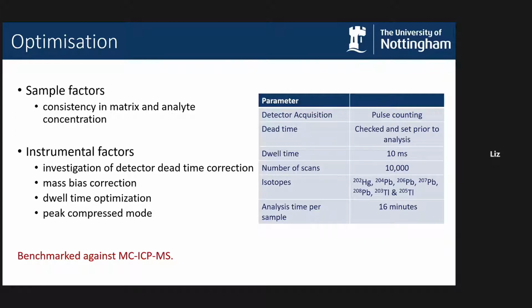And we also investigated peak compression mode and not using peak compression mode, and found that that actually made very little difference. So I won't say anything more about that. In the table on the right-hand side of this slide, I show you the optimized parameters, the isotopes we measured. And we were down to an analysis time per sample of around about 16 minutes.